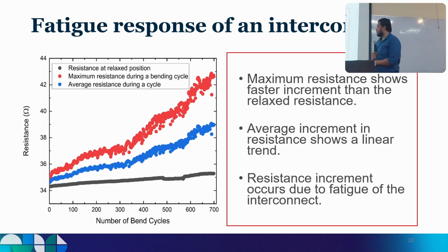Average resistance means the complete data over a cycle was taken and the average resistance was calculated for that data. We can see that it has a more linear trend compared to the red, which is the maximum resistance. It is more linear and also has less noise. It also shows a significant increase compared to the resistance at rest. So I selected this average relative resistance increase as my response to carry out my analysis.